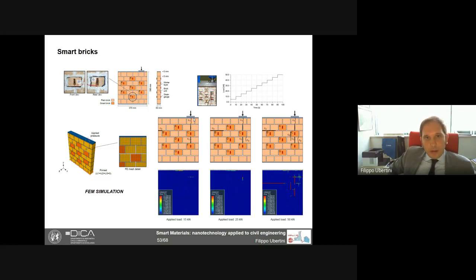We apply the load on the right side of the wall in eccentric position, and we induce some damage. In this slide, you see a comparison between the real damage, real cracks C1, C2, and C3 observed on the structure at different loads, 15, 25, and 50 kilonewton. And below, you have a numerical simulation that resembles the experiments very well, with a micromechanics approach.